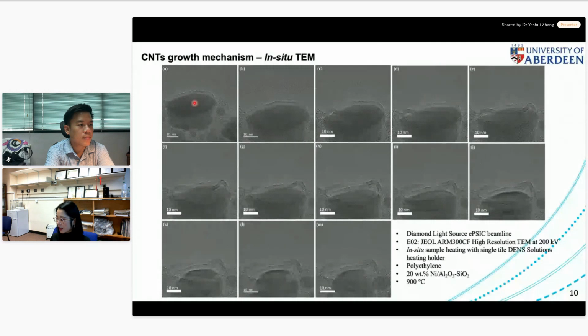So that is a catalyst particle, and on the surface, you could see in the first image we captured, we can really see the carbon atoms being formed on the surface of this catalyst particle. And later on, you can see this layer has been growing up. And later, from figure C over here, you start seeing some structure of these hollow carbon nanotubes. And this tube is being extended in such a way until we can see the length.